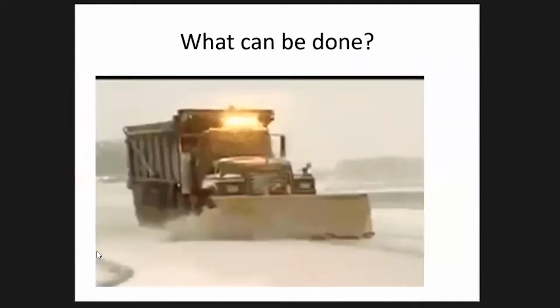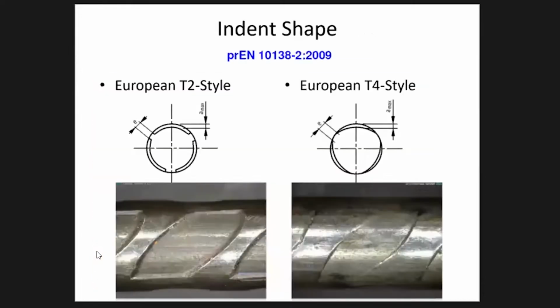Okay, a small amount of displacement is not too bad. We have a lot of displacement, that can be problematic, right? So if we have to displace, what can we do? One of the things is for that snowplow, if we don't want to displace as much material, make it shallower, right? Make our indents less depth. That's one thing. The other thing we could do is, instead of having a rectangular area that's approximate area B times H, we could taper that off at the sides, okay? We'd have half the area. And that's exactly what's done with the European style indents.